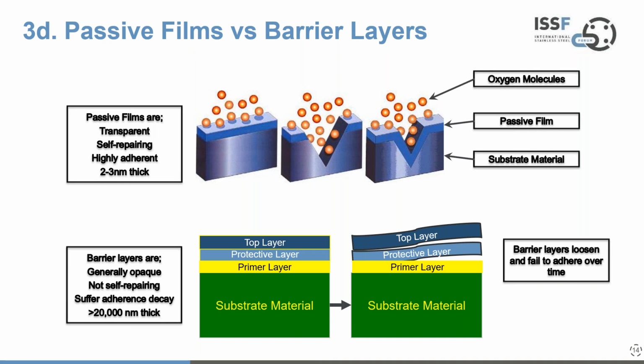But the presence of oxygen means that passive film will immediately repair itself. Even though you've got a groove in the material, you've at least re-established the passive film because the oxygen molecules combine with the key element, in the case of stainless steels, chromium, to form that oxide on the surface that, as we said, was tightly adhering.